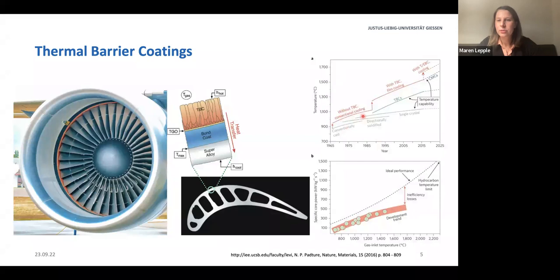And this graph you've seen before, so with time or over the years, the operating temperature increased. However, the specific core power with increasing gas temperature or operating temperature deviated even more from the ideal behavior here. And this is due to the active cooling, which is used to be able to obtain higher temperatures, but one loses some specific core power, and therefore new materials are needed which can either withstand higher temperatures or which have a lower thermal conductivity, or both in the best case, so that one can go to higher temperatures without active cooling.